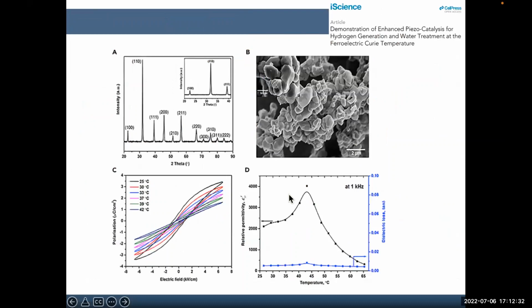So at Bath, really just to try and understand the process, inspired by Professor Haito Huang, we looked at BST as a material. And I like the BST material, barium strontium titanate, because it has a low Curie temperature. Remember, the Curie temperature is when it changes from a ferroelectric phase to a cubic symmetrical phase. And so for BST, it's about 45 degrees C. So this material changes phase from ferroelectric below 45 to non-ferroelectric, a paraelectric phase above 45. And what it allowed us to do is to look at the response above and below the Curie temperature, just to be sure that there's some ferroelectric contribution to what we're producing in terms of the chemistry of the system.